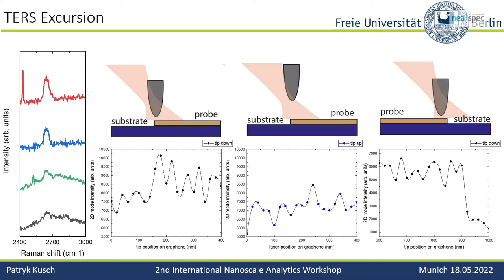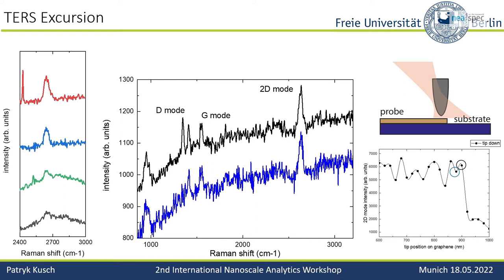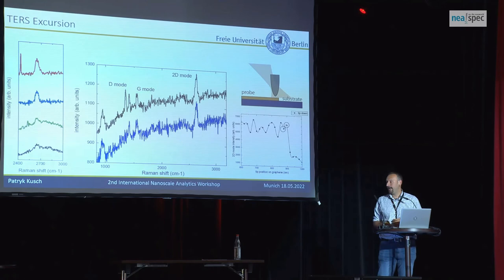The ultimate proof is if you are lucky and have a point scatterer. A graphene edge has a lot of defects, and when we go to the graphene edge — exactly at the edge — the D-band appears. When we are 20 nanometers to the left or 20 nanometers to the right, the D-band is completely gone. I'm not entirely sure what it is — I think I had something on the tip during those experiments. But this is a proof: the D-band only appeared when the tip was at the edge and approached; otherwise we never saw this D-band.